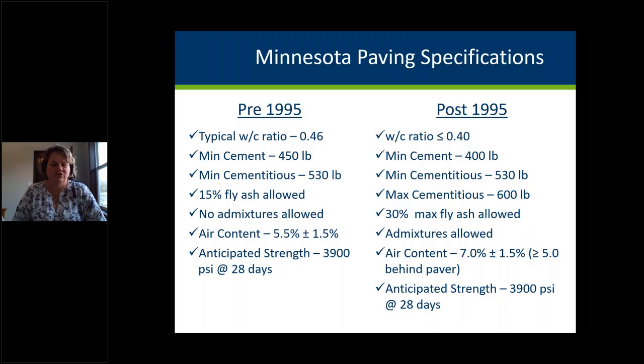We allowed admixtures. Water reducers made a huge impact on reducing the water cement ratio without a lot of other changes, and we increased our target air content to make sure we had enough air.